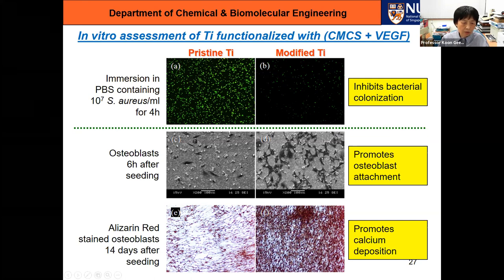And this last row is very important because this is calcium deposition. It is the function of osteoblasts to promote calcium deposition because these are bone cells. And the brown color denotes calcium deposits. So this is after 14 days. And sure enough, we have calcium deposited on titanium, pristine titanium. But you can see on the modified titanium, we have much more calcium deposition.